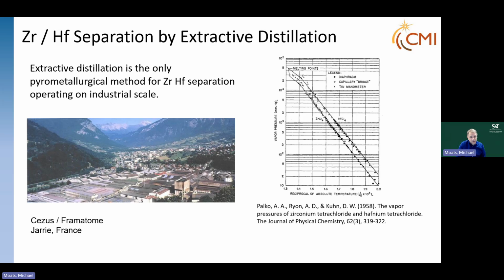So the French nuclear industry was working closely with the United States industry in the 1960s and 70s. And in fact, the first hafnium zirconium separation plants in southern France were very much similar to the U.S. Bureau of Mines process or the Oak Ridge process. And along the way, they decided they wanted to do something different. There are differences in the vapor pressure of zirconium tetrachloride and hafnium tetrachloride. Now, if you just do it by itself, this is what the plot looks like. At any given temperature, the vapor pressure of the hafnium tetrachloride is a little bit higher. So you could maybe volatilize the hafnium away from the zirconium.